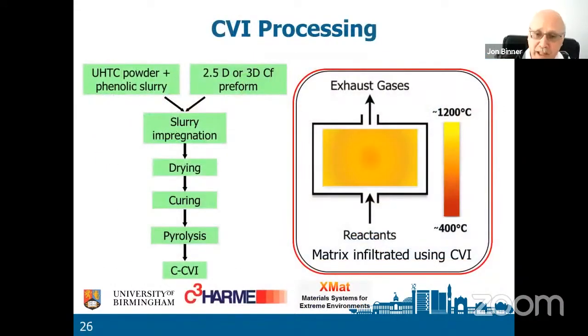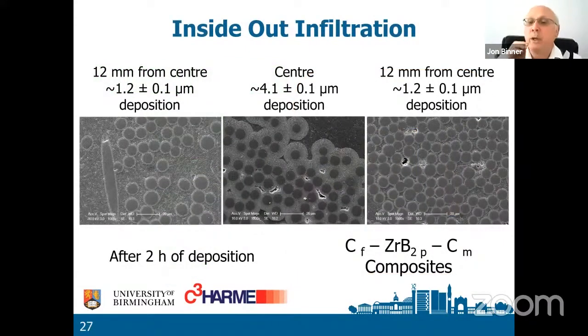Okay, so we've seen this slide before. We've done the slurry impregnation. We dry everything out. We cure the resin that's in there. We pyrolyze the resin, and that gives us some carbon. And then we use the CVI system to deposit the rest of the carbon matrix. We use RF processing now, not microwave, because we are using carbon fibers, and carbon fibers absorb RF. Silicon carbide fibers absorb microwaves. So the different frequency, different wavelength applies to different materials.